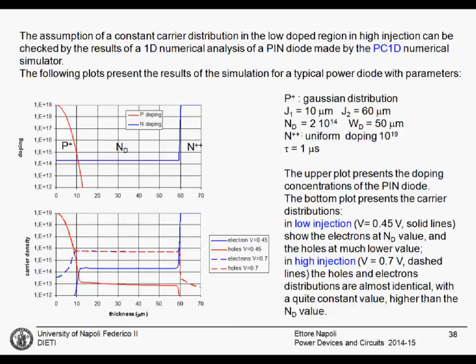What we see in the bottom plot is the carrier distribution for two different cases, 0.45 volts applied to the device and 0.7 volts. The first case is low injection. We have the solid lines for the low injection. As you can see, in the P region, the holes follow the doping. In the N region, the electrons follow the doping, and the holes are much smaller, 10 times, 20 times smaller than the doping concentration. In the N plus region, the electrons follow the doping, and the holes are negligible, much lower than 10 to 12.